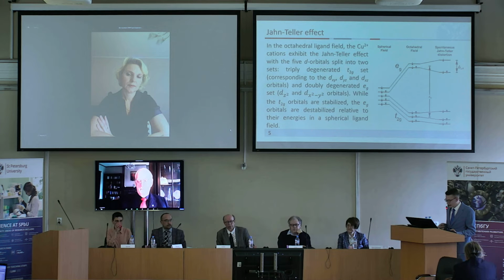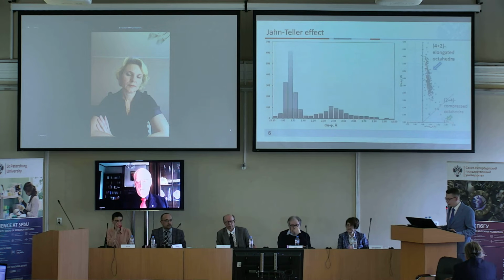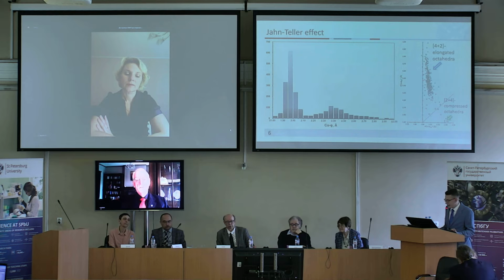Depending on the particular orbital occupied by a single electron, compressed or elongated octahedrons can be formed. The study of the distribution of bond lengths reflects the dominant nature of elongated octahedrons. On the right, you may see a graph of the dependence of the average lengths of apical bonds on the average length of equatorial bonds, where the circles indicate the elongated octahedrons. As you can see, the greatest number of them is observed.